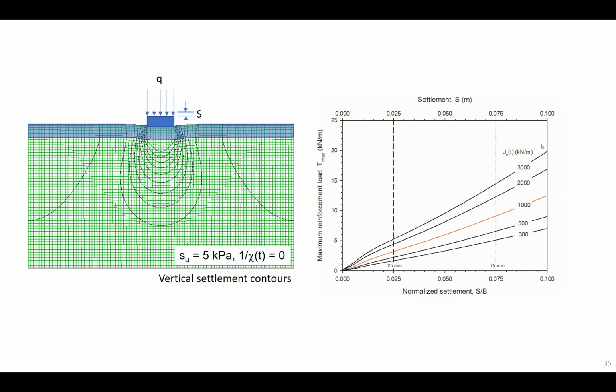And the other thing we were able to do was, okay, we're interested in the pressure settlement response, but what about what is happening to the reinforcement itself? So here we are with a material that essentially doesn't have any curvature in the secant stiffness curves, and we're just looking at the effect of J0. This is the maximum load in the reinforcement on the vertical axis, and then we have displacement on 2 axes in the horizontal direction. And the red trace is a typical reinforcement with a J0 value of about 1,000.